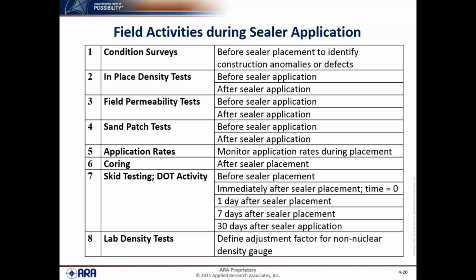So on the State Route 47, because of the heavy traffic, especially during business hours, the 30 days after sealer application, that was the only one. State Route 47, I think, was the only project where skid values after 30 days were not tested. So we also then did lab tests on the cores to measure the bulk densities and the maximum specific gravities. And that was used, as I said earlier, as an adjustment factor for the non-nuclear density gauge to make sure it's reading the same.